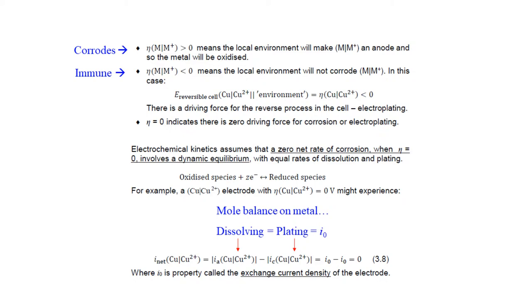But in fact, electrochemical kinetics assumes that when you have zero net rate of corrosion, when you have polarization equal to zero, what we actually have is a dynamic equilibrium with equal rates of metal dissolving and plating. So we can imagine, in the equation that follows, this copper metal block, and the reason that the net corrosion current density for copper to copper 2+ is zero is that it's equal to the rate at which it dissolves, this anodic current density, minus the rate at which it plates out, this cathodic current density. Both have the same value, and they're equal to this i subscript zero, called the exchange current density of the electrode. So that's the rate of both the forward and backward corrosion processes when the copper to copper 2+ electrode is at equilibrium.